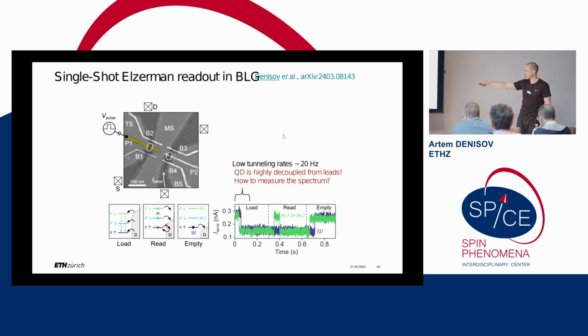You can also notice for this device that the loading time, so the time it takes for an electron to tunnel into the dot here, is very long. It's about 50 milliseconds, meaning that we managed to make a quantum dot which is highly decoupled from the leads. So the tunneling rate was about 20 hertz, meaning that only 20 electrons per second can enter your dot. In order to do it, you really need to push your barriers down, so you really need to confine your dots, which usually means that your spectrum changes compared to when your barriers are so open that you can measure finite bias spectroscopy and see the spectrum which I showed a few slides ago. So once we quenched the barriers so hard, we weren't sure if we still had this textbook spectrum which we wanted to study.